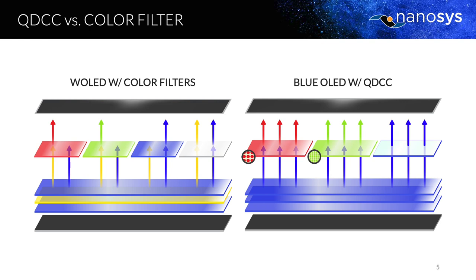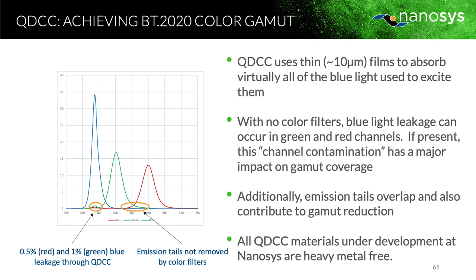There are challenges with this. So the thickness of the material that's at the front of the display has to be very thin. The black matrix and the color filter material that's at the front of a display is very thin, about 10 microns. And the requirement is different than in QDEF. In QDEF, you wanted some of the blue light to penetrate to make white light. In this case, you want to absorb 100% of the blue light and convert all to the desired color.